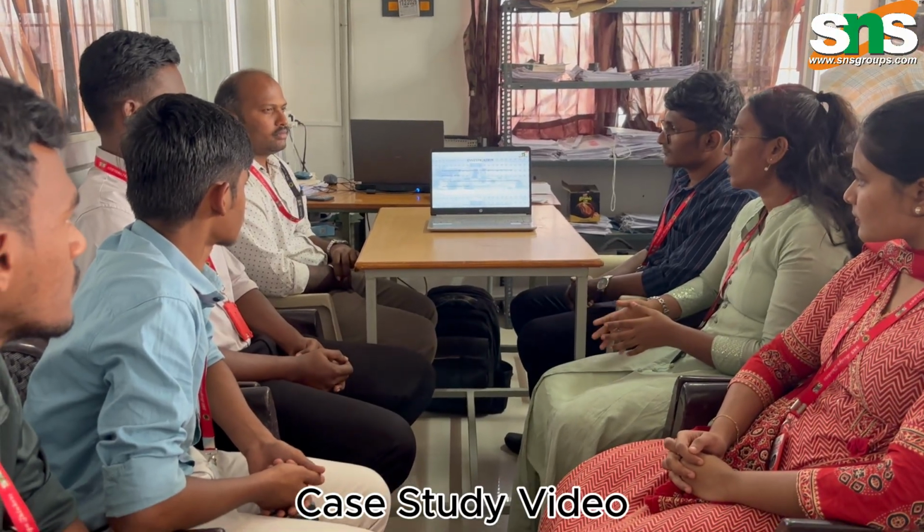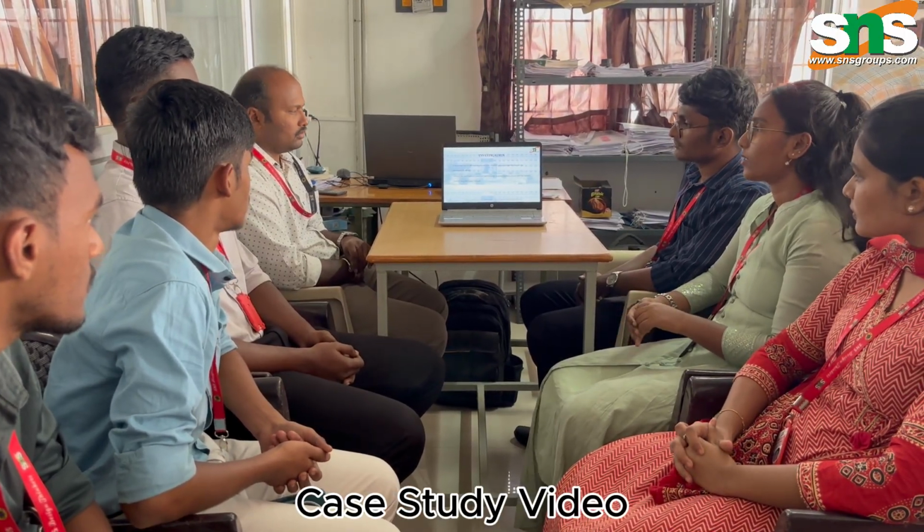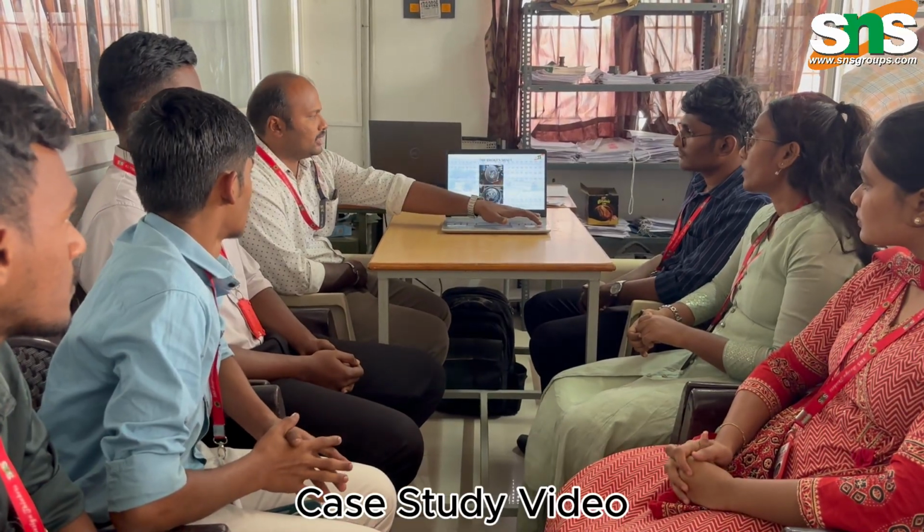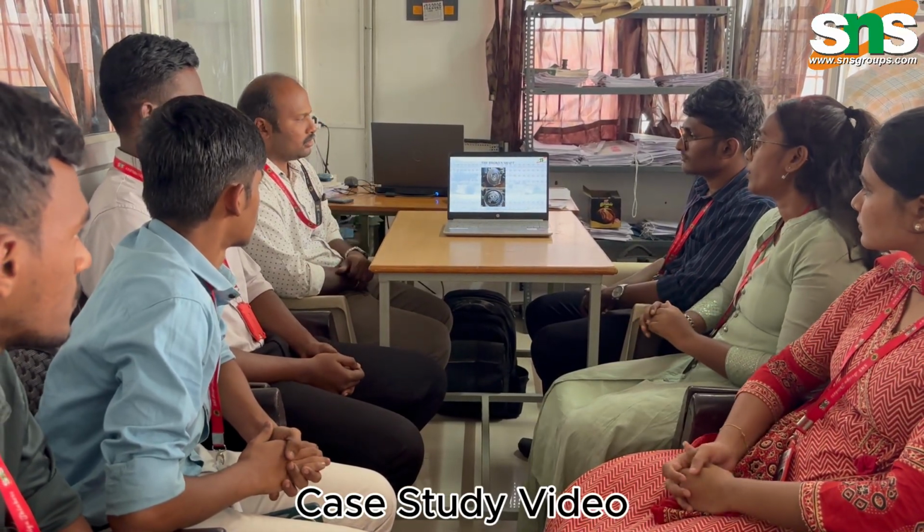For the investigation, it was found that the fillet radius present at the fracture's origin was smaller than the one provided by the design. Although the shaft had been quenched and tempered, its actual hardness did not have the optimal value for long life fatigue strength. So this is the picture of the broken shaft.